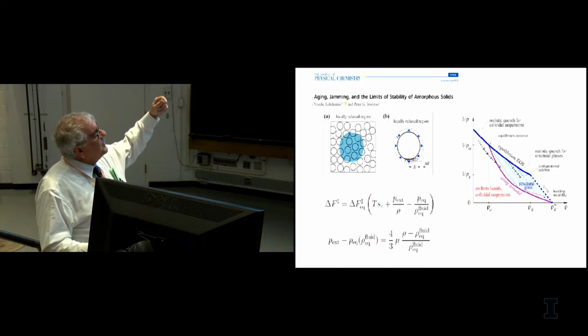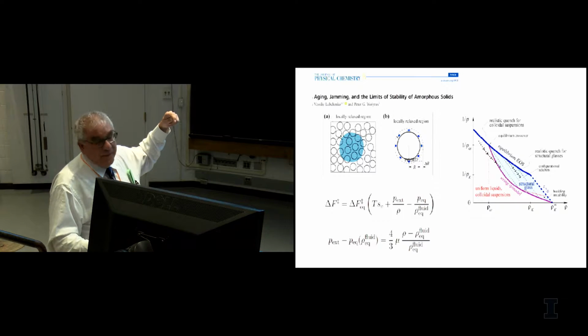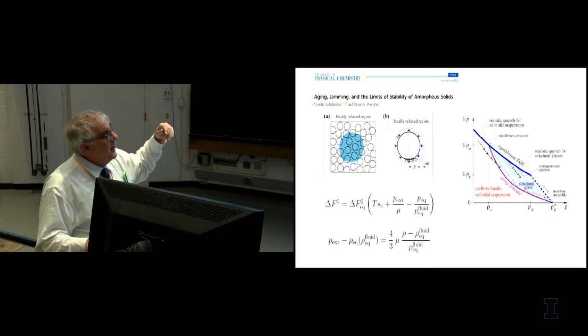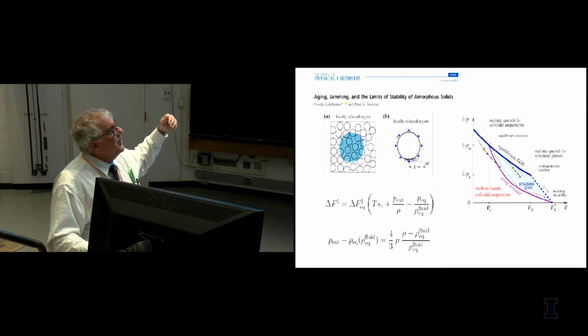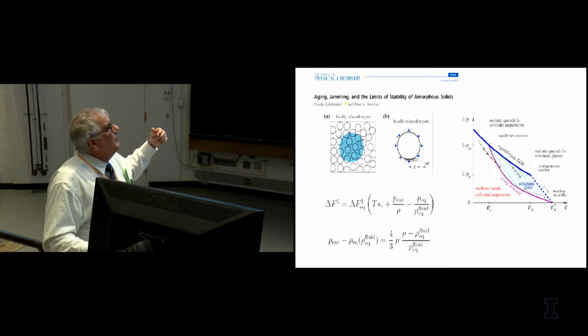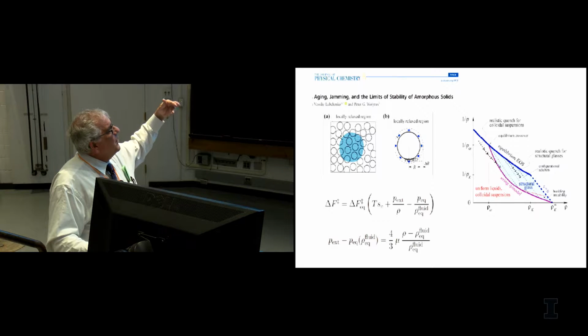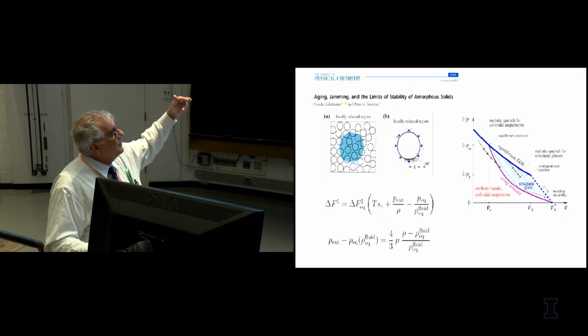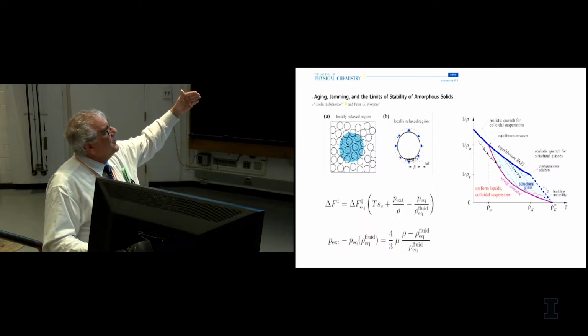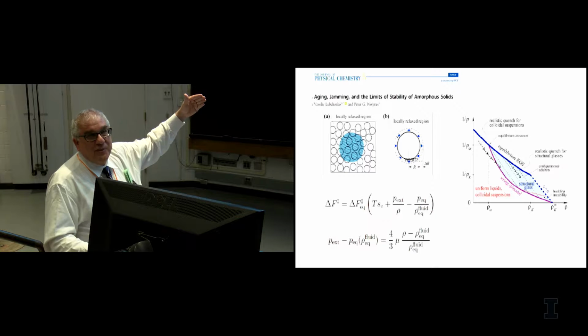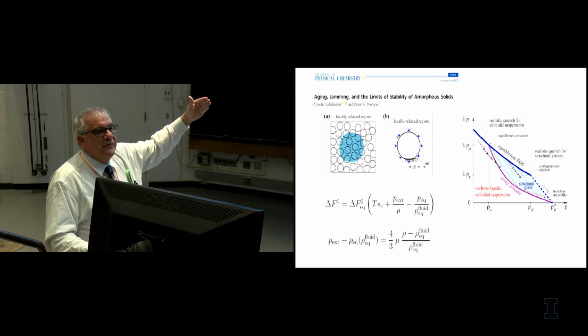And now what you find is a very interesting kind of diagram. Some people would call this a phase diagram. In mean field theory, it actually is a phase diagram. But in this theory, which goes beyond mean field theory, it turns out we just have to call it a diagram. And the reason is that most of these states are not equilibrium states. They're states that have, say, pressures quite different from the equilibrium pressure, which can happen if I'm able to cool something really, really fast.